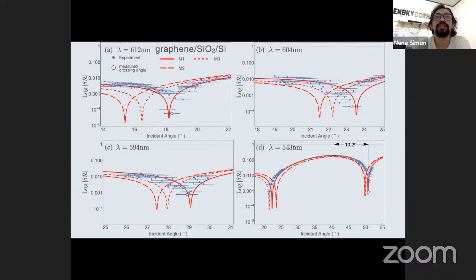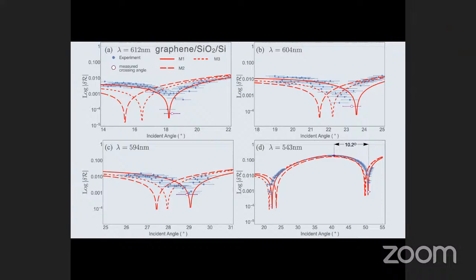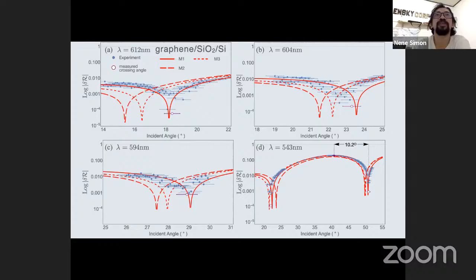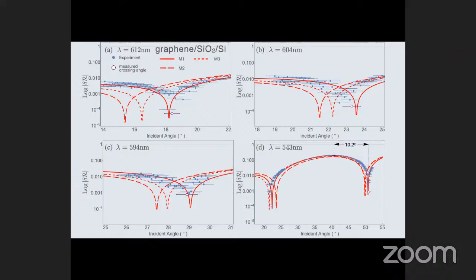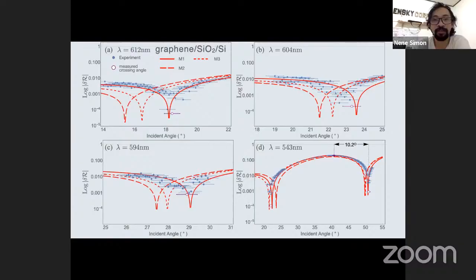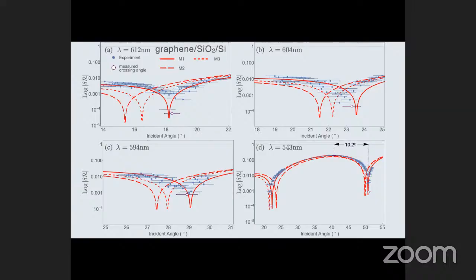But in the case of graphene, although it's just an atom thick, it is conducting, so it can greatly affect the absorption properties of the sample. The presence of graphene can actually shift the position of the crossing angle significantly. So it can override any effects of the water vapor.